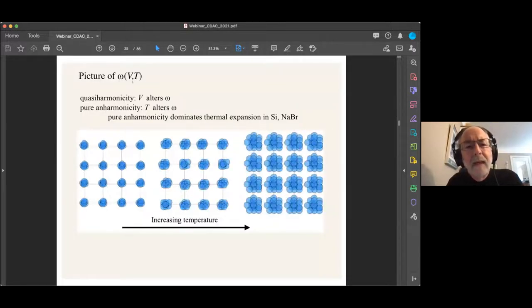Basically, we have two effects of the frequency versus volume and temperature. The quasi-harmonic effect, the volume alters the frequency. And pure anharmonicity, the temperature alters the frequency. Now, when we do the anharmonic calculations, we actually include both. But we found the pure anharmonicity really dominates the thermal expansion. Here's the idea. You have interatomic forces and vibrational frequencies that depend on how far apart the atoms are as the volume expands, and also on how much they're moving about their center sites. And this temperature effect turned out to be dominant here, pure anharmonicity.